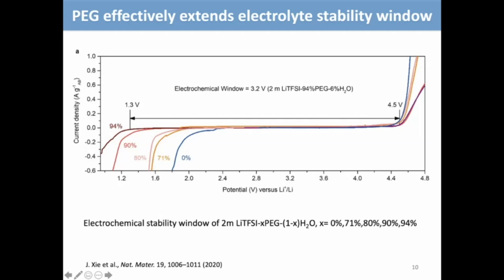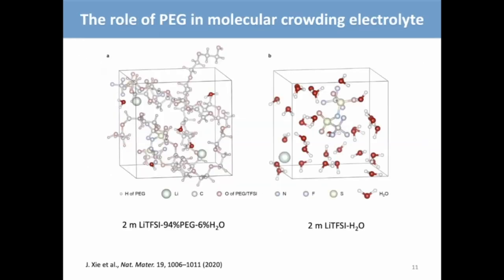So with that, we're able to achieve a 3.2 volt window with a low concentration of the salt and using the molecular crowding agent to stabilize the water. So we use DFT to understand the water environment in the molecular crowding electrolyte versus the regular electrolyte.